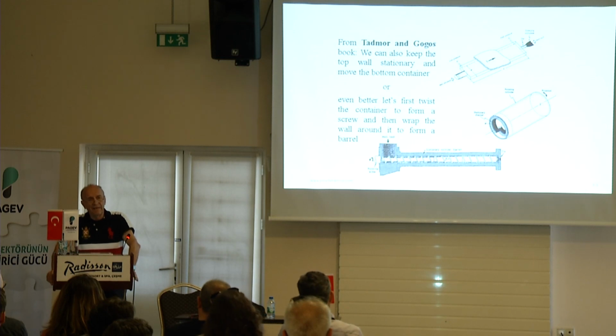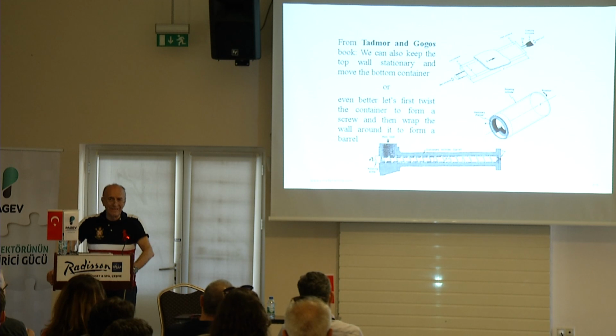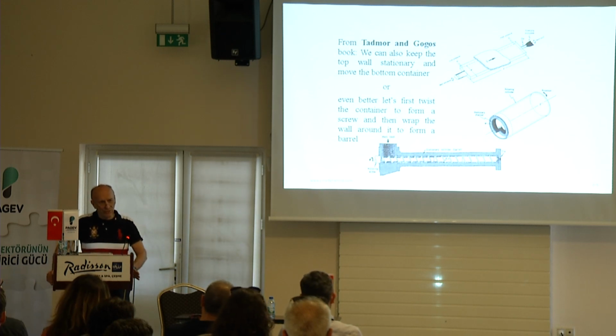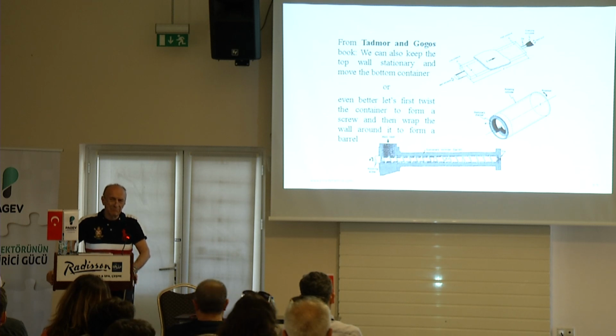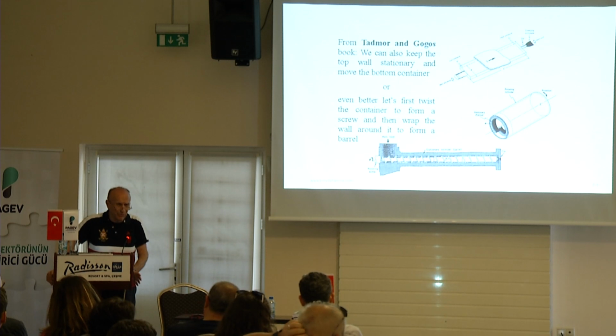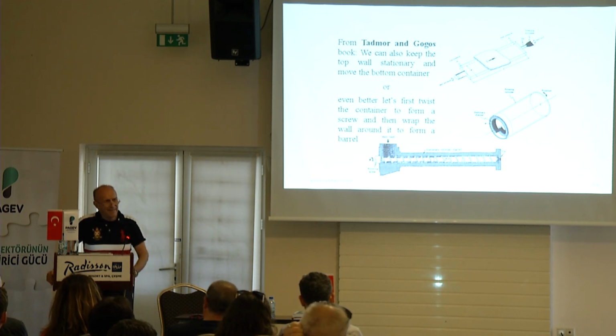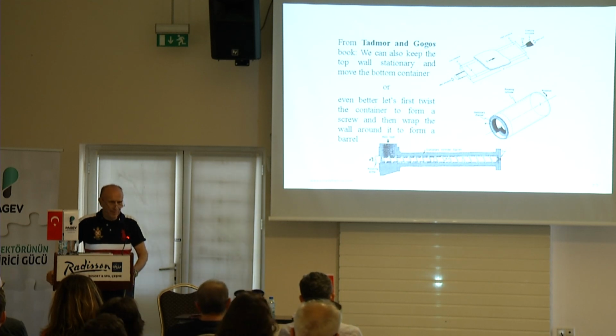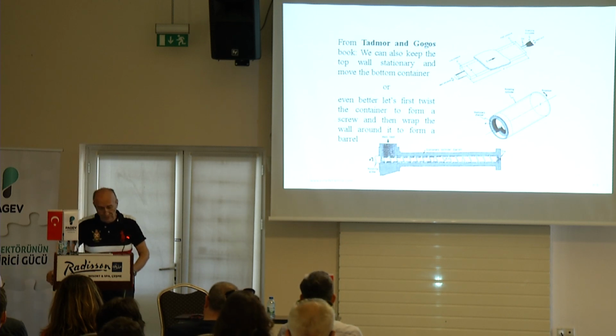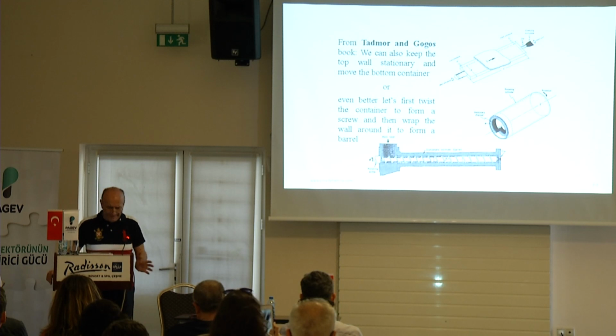Some people say, Greg Campbell is one of them, that rotating the barrel and rotating the screw is not 100% identical. He's got some arguments. The result is that if the screw is shallow, has shallow channels, there's not really much of an effect. If it's a very deep screw, yes, there is an effect. But in extruders, the channel is shallow. It's not very deep. So there's no question that the approximation which I'm going to be using here, and I'm also using it in my software, of rotating barrel, stationary screw, is really valid. But there is a point that if it's a very deep channel screw, there might be some differences.